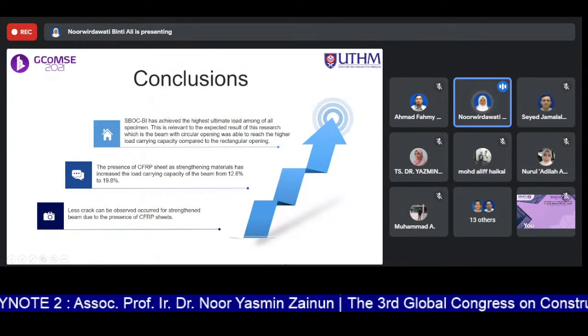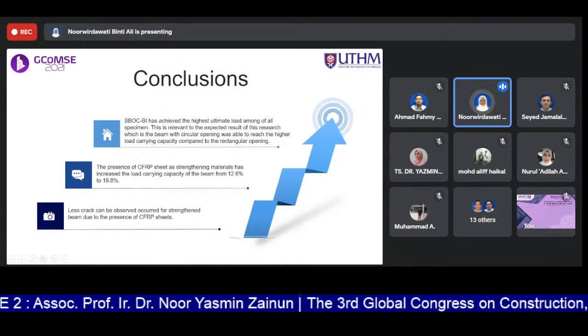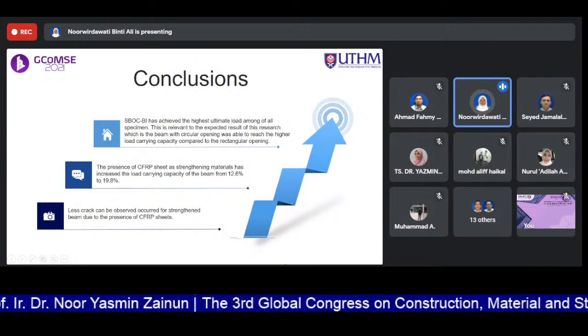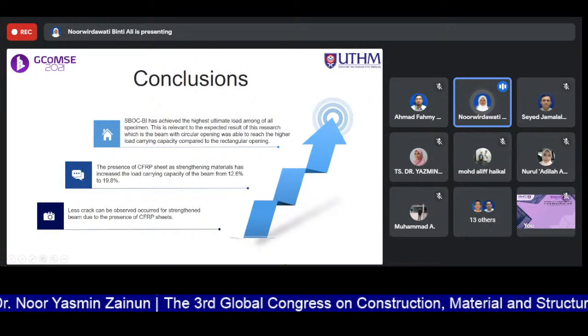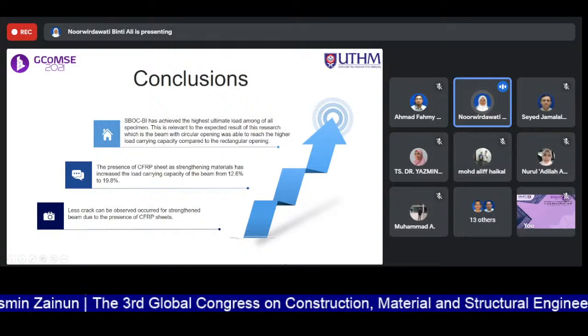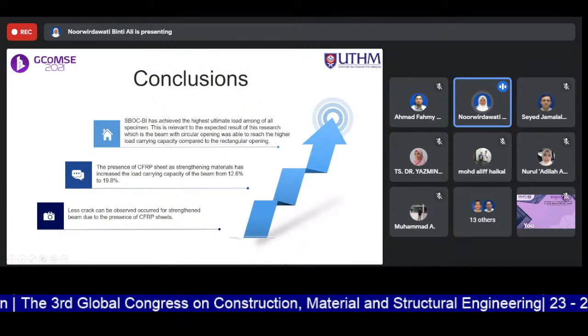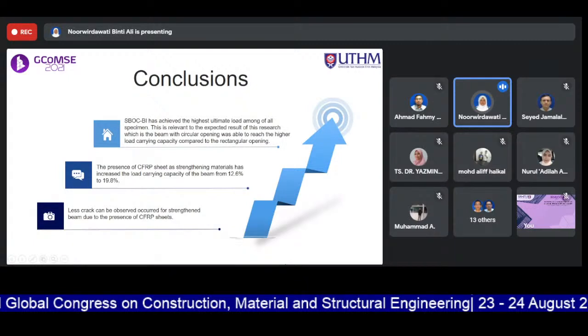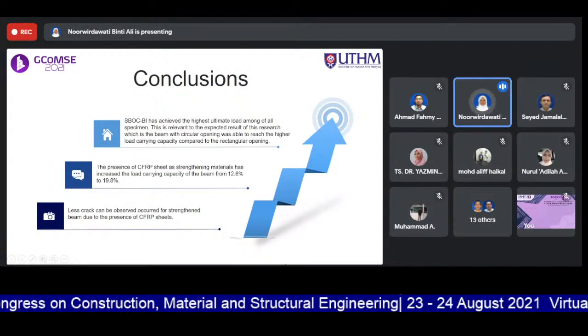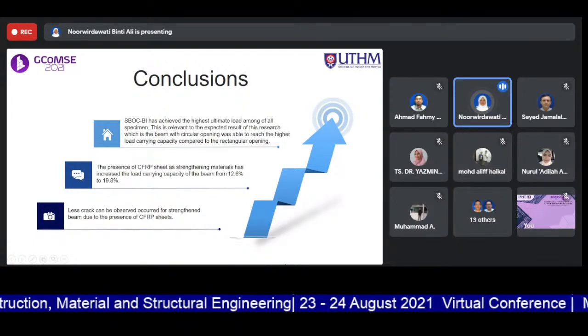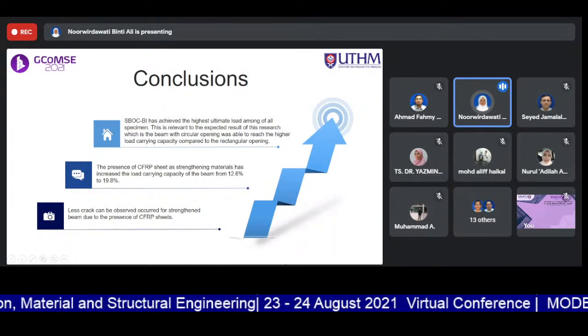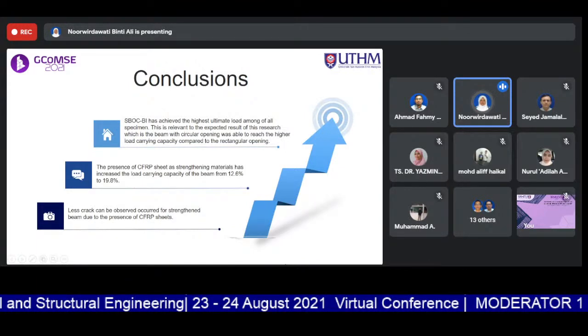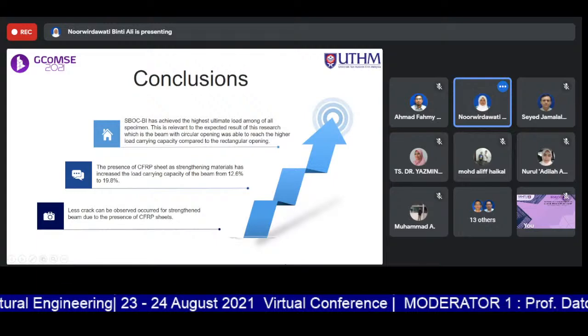A second conclusion is that the presence of CFRP sheet as strengthening material has increased the load carrying capacity of the beam from 12.6% to 19.8%. And last but not least, less crack can be observed for the strengthened beam due to the presence of CFRP sheets. And that's all from me.